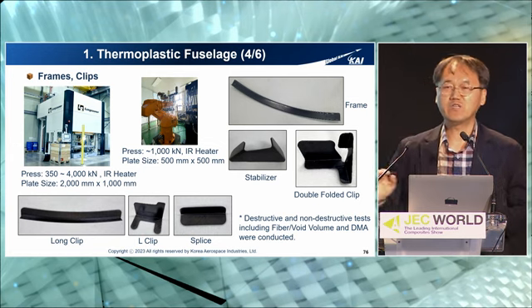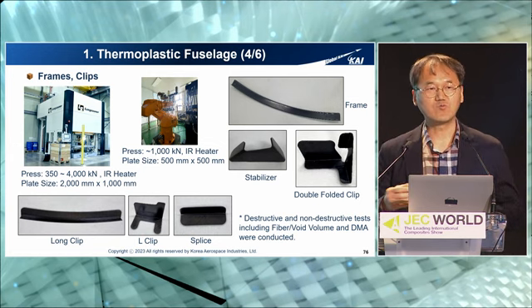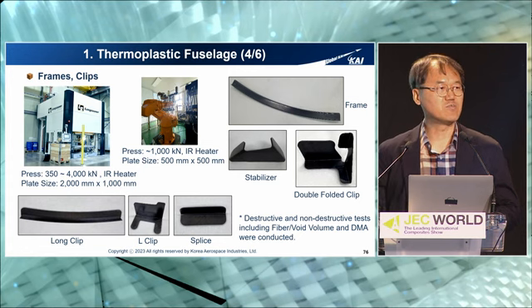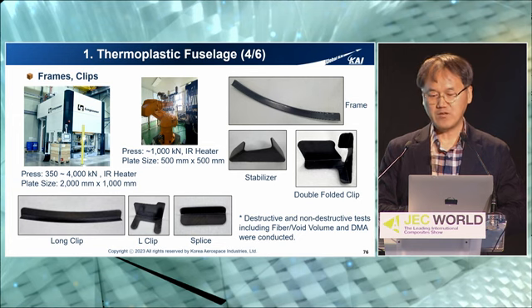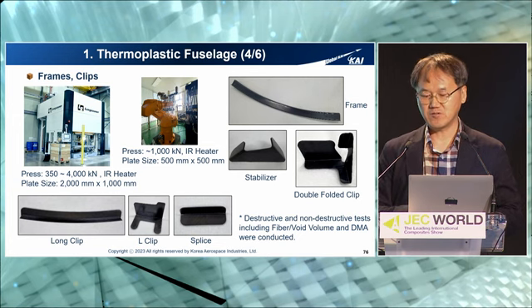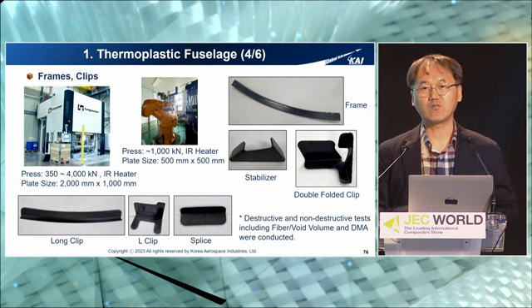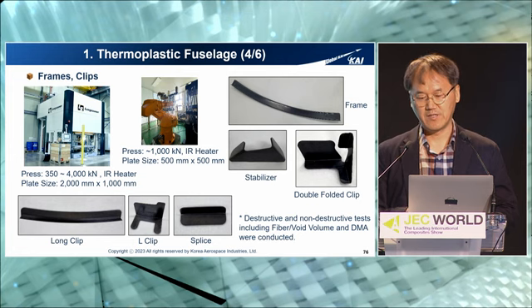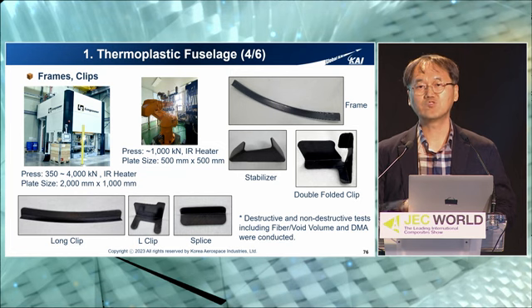The difference from the previous technology is we used unidirectional tape, not fabric prepreg. We conducted destructive tests and non-destructive tests to check internal defects and quality issues, and void volume and DMA tests were also conducted. Most of the results are within our expectation.